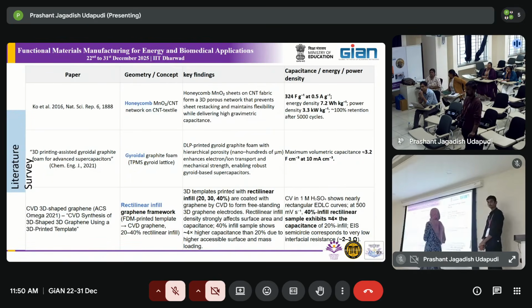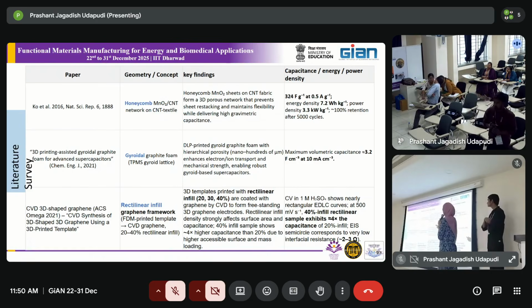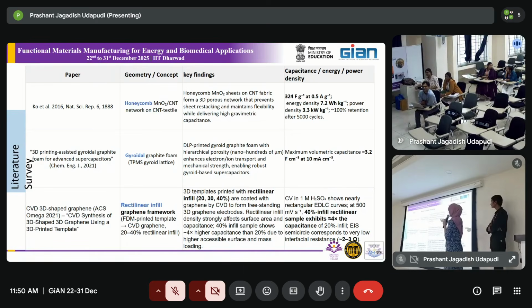So these are some of the literature that I have come across. The first one is honeycomb, gyroidal and rectilinear. By using honeycomb, they have used a honeycomb pattern for MnO2 and CNT, and they have created a 3D porous network, and they have also obtained a very good capacitance, like 324 farad per gram at a current density of 0.5, and then the energy density and the capacity retention. Even after 5,000 cycles, they have retained a specific capacitance of 324 farad per gram, that is 100% retention.